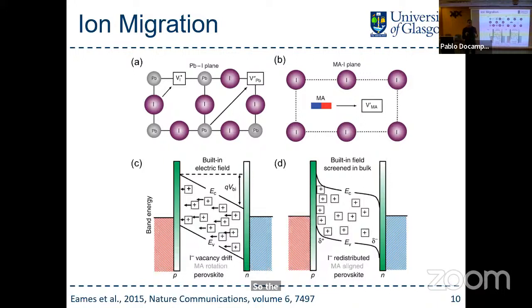This is why you can't just take a classic semiconductor physics model like COMSOL or whatever and plug in a device; it doesn't work. You need to use drift-diffusion, anything that takes into account the movement of these ions. In terms of the physics of the material, when we apply an electric bias, those ions will move to the grain boundaries, to the device interfaces, to screen off this external bias, and that will shift your bands.